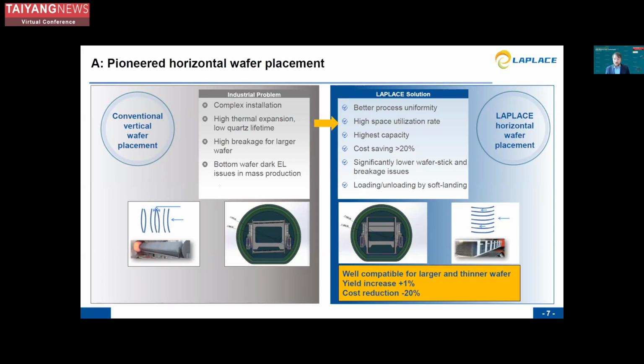This leads to a cost saving of around 20%, and we get much lower wafer sticking or breakage issues in the systems. And this is even supported by what we call a soft landing when we load and unload. Like this, we can use larger and even thinner wafers and could increase yield by about 1%. And as mentioned, a cost reduction of around 20%.